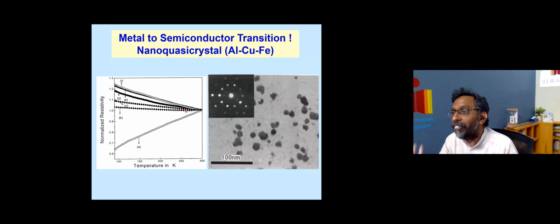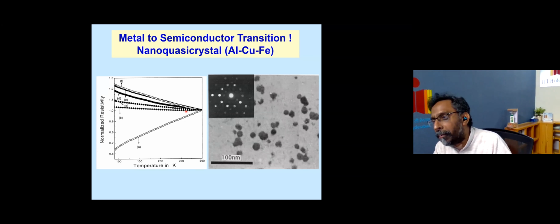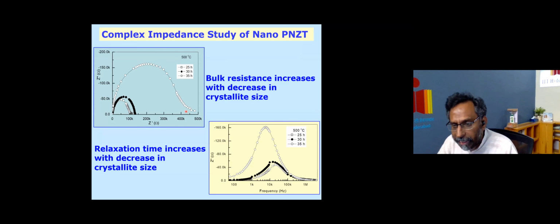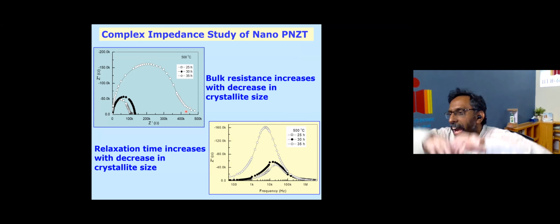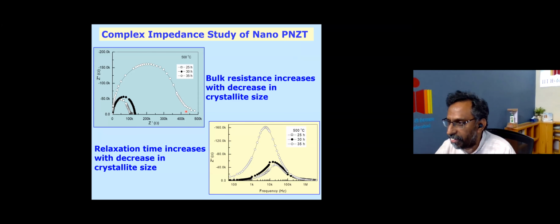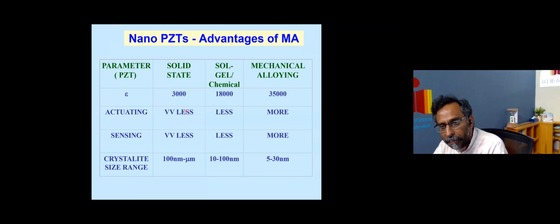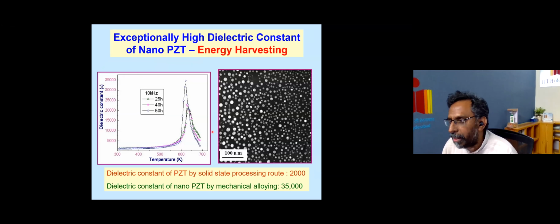So I can make different colors out of this. Lasers of different colors are coming up nowadays. All this is happening because you are able to make materials with different band gaps. And we can make materials with interesting properties. This is one such piezoelectric material called lead zirconate titanate, PZT, and by making it nano, suddenly its dielectric properties significantly change. We can demonstrate that this is a PZT material.